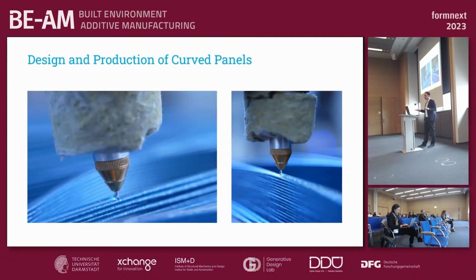That is totally fine when it's cooled down, because then we go to a second lamination process where we stack up the glass with the core structure, and then we put it into the oven, and then we are laminating the core and the print together.